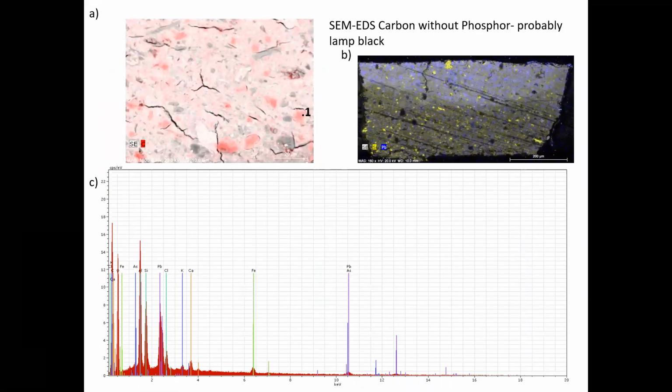Contrary to Portuguese painting, the phosphorus that was not found indicates that it's probably lamp black that was used to perform this background. Portuguese paintings will often have bone black as the main component, and this bone black is recommended by collaborator treatises. This pigment was not found in both Goan paintings.